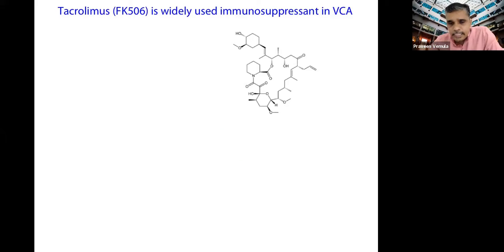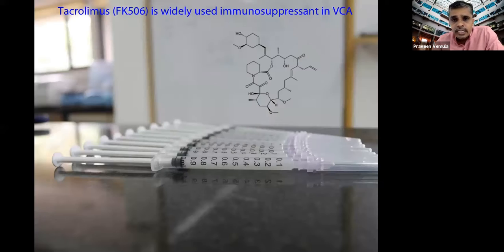Then what we have done is we took tacrolimus. Tacrolimus is a known immunosuppressant drug, which is prescribed for hand transplantation patients. And we optimized conditions to encapsulate it within these gels, and we developed these injectable hydrogels encapsulated with this immunosuppressant.